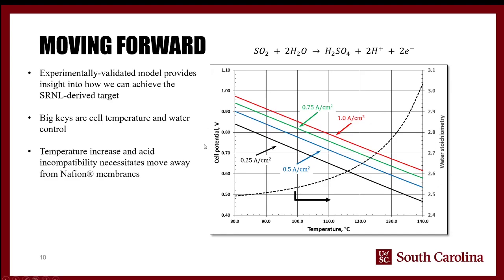And so this one figure is kind of the big takeaway here. And what it actually shows is that we can hit, at least in theory, the target of 0.6 volts at several different current densities. So the one that we're aiming for here is the 0.5 amps per square centimeter. And the theoretical model says that we should be able to achieve that if we can raise the temperature of the electrolyzer to approximately 127, 128 degrees Celsius. So we can call it 130.